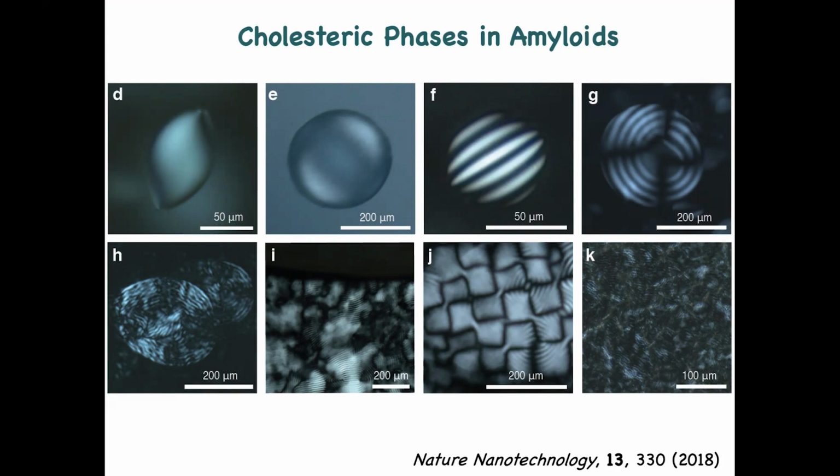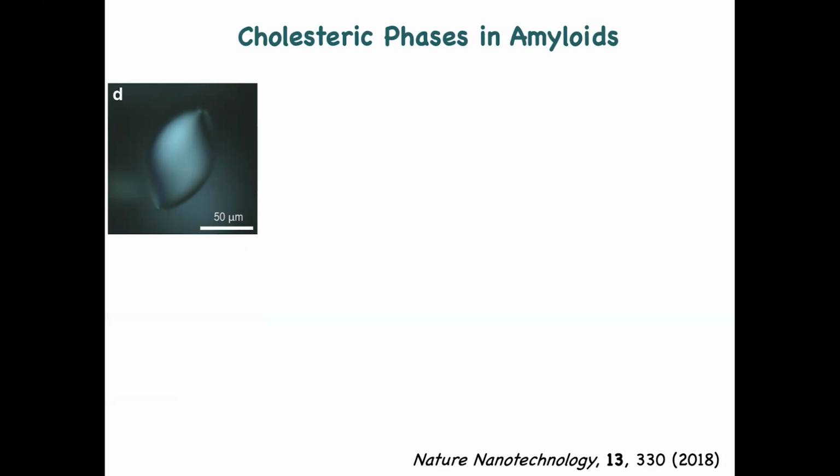So I'll just start to look, for example, at the simplest one, which is this one, which is already extremely complex because we are used to thinking of a droplet as a spherical object. But in this case, you have a nematic field that is uniaxial, so it would like to have a cylindrical object. Surface tension wants to close it into a sphere. What do you have in the end? If you minimize things, you have something like a rugby ball. But for this rugby ball to emerge, the surface tension must be extremely small.